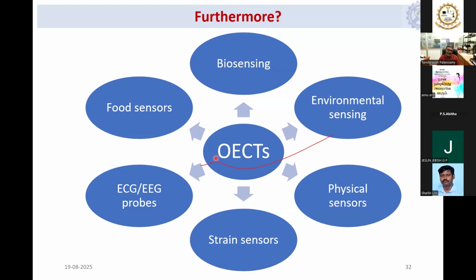You can use OECTs for ECG, EEG probes, because here the gate electrode is very sensitive. Even a small change in potential at the gate, the channel current will be affected significantly. So this can be pretty much used as an EEG probe, where the measurement is the voltage only. On the other hand, you can also use it as a physical sensor, like a pulse sensor and so on. And you can use it as a strain sensor, because when you strain the gate electrode, or when you strain the distance between your gate and the channel, then obviously the capacitance is changing. Then that will give you a very amplified signal.